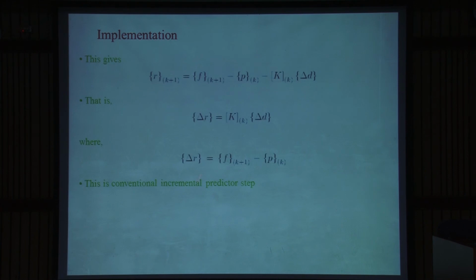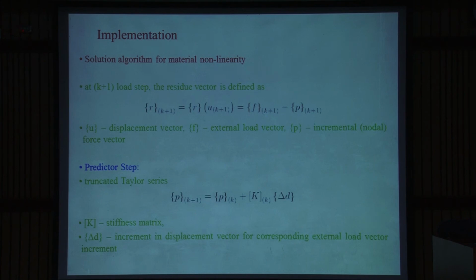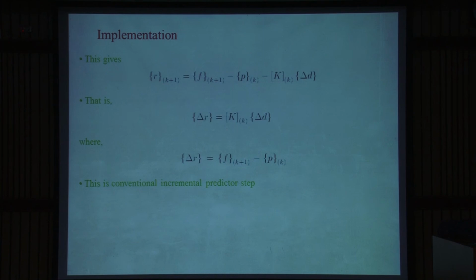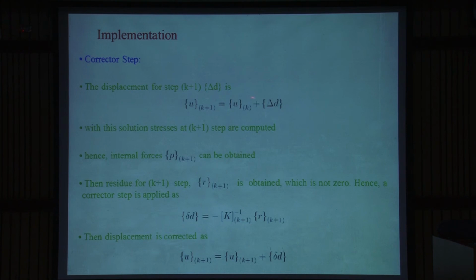So if I go back and put this here, then I will get this. This equation will give me this delta r residue. So this is your conventional incremental predictor step. Now in the corrector step, your displacement for the k plus 1 step is updated as u k, that is the displacement at the previous increment, plus whatever displacement you have got for the current load increment. Once you have this solution, you can obtain the stresses, and once you have the stresses, internal forces are obtained. When you are obtaining the stresses, there is one more step, that is you have to update your damage indicators.